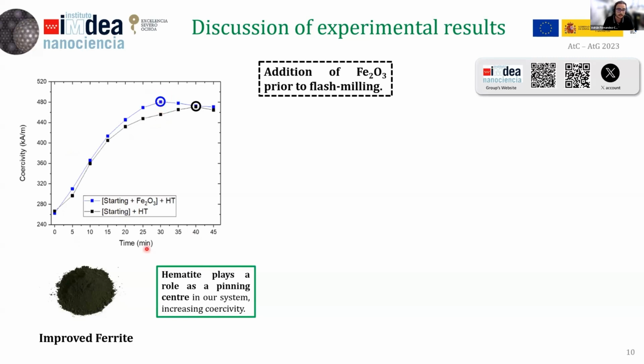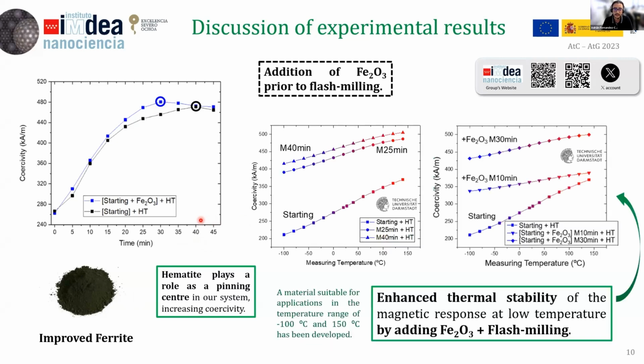So here we can finally say that the hematite plays some role as a pinning center in our system, increasing coercivity of this improved powder. So further study was made by our collaborators of the TU Darmstadt. They performed VSM measurements at different temperatures, and here you can see the coercivity response of different samples. For example, here we can compare the starting powder with the 25 minutes milling and 40 minutes milling.